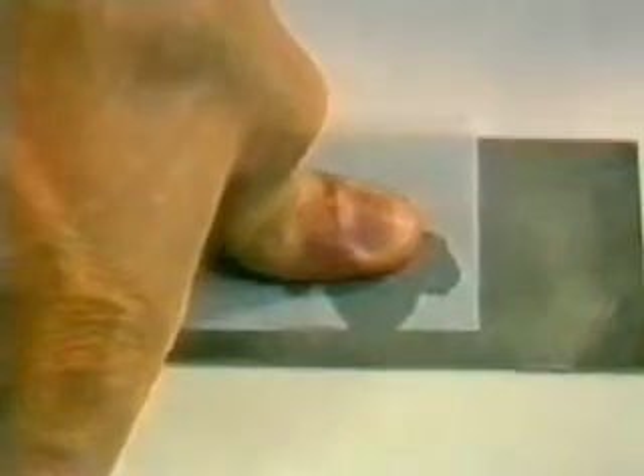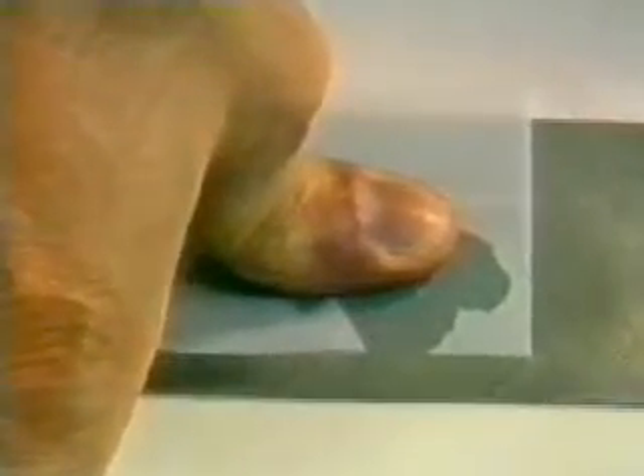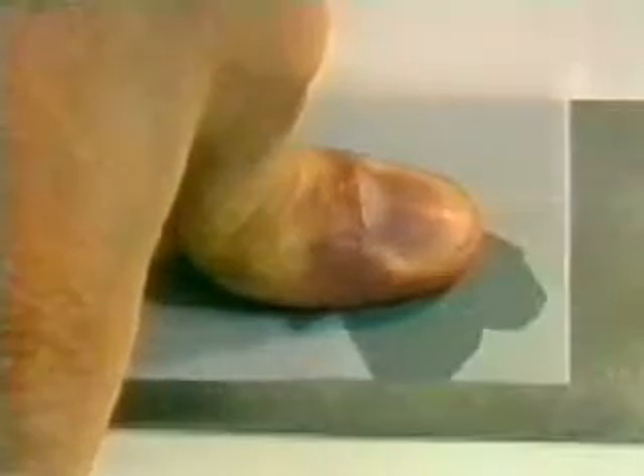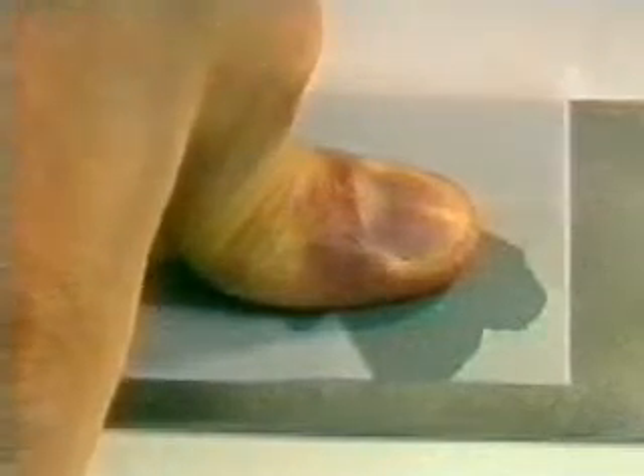One drop of adhesive is sufficient for all normal-sized strain gauges. It's applied to one side and then uniformly and thinly distributed over the whole bonding surface with the Teflon strip in one movement. When doing this, no pressure should be exerted on the cement. Then the strain gauge is immediately folded down with a rolling movement of the thumb. It's then pressed and held steady in this position. The Teflon film prevents the thumb from becoming stuck as well. The thumb pressure must be uninterrupted and applied over the complete bonding surface until the adhesive has cured. At room temperature, this takes about 1 minute.